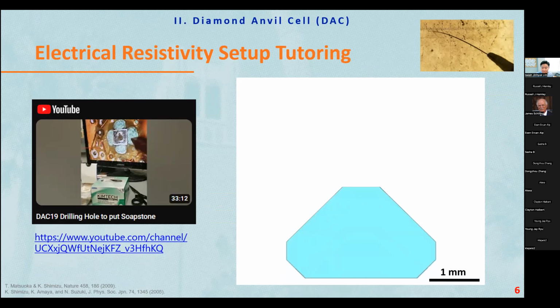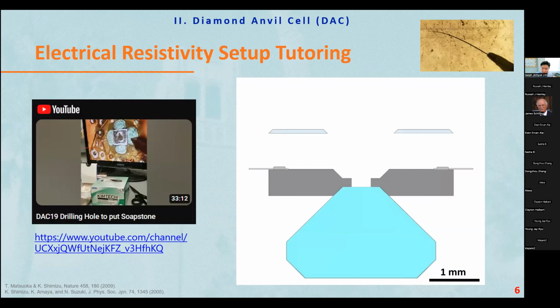So we need diamond and gasket at the center, very nicely centered diamond, and then gasket, and then we put the electrode on top of the gasket so that we can check any short of the sample itself with the metal gasket. And that is very important so that we can remove the additional resistivity in our measurement. And we put Scotch tape on top of this electrode and put another Scotch tape covering most of the area of the metal gasket. And then the insulation layer, we mostly use the cubic boron nitride with an epoxy mixture.